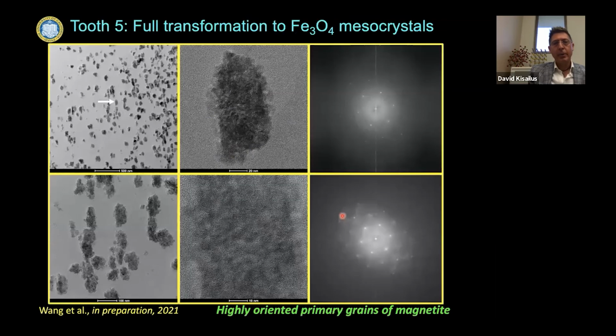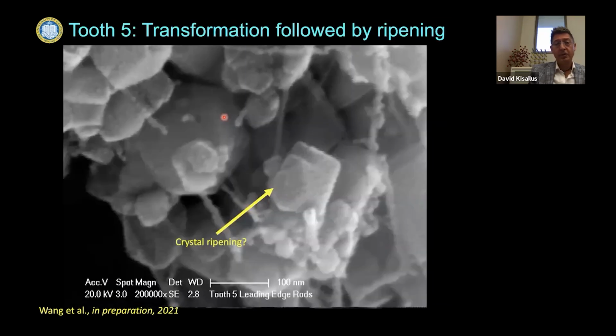And eventually, by tooth 5 and certain regions of tooth 5, that transformation is now complete to all magnetite, and it still maintains this mesocrystalline structure. But eventually, those rods have to form, and that mesocrystalline structure will undergo Ostwald ripening.